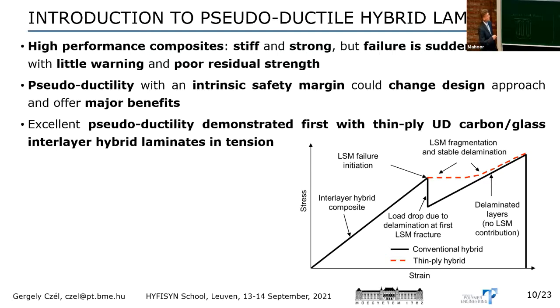But if we have thin plies in our hybrid composite, thin low elongation plies, we can have fragmentation, and that can provide us with a stable plateau in the stress strain response, and then we can further exploit the strengths of the high elongation layers. And this is what we call pseudoductility. So it is not real ductility at all, because all fibers and all